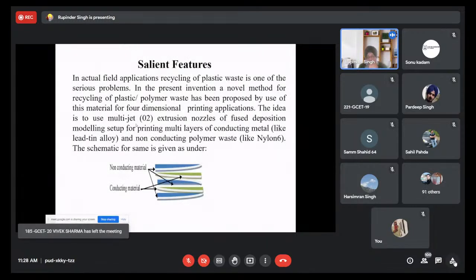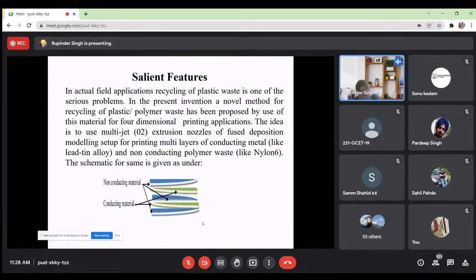Now the 4D part, this is derived from a very simple experiment of the first year in my BE program. Here what we did is we printed some layers like this. Here is a non-conducting layer, then the conducting layer, then the non-conducting, then the conducting, and then the non-conducting. Basically, the idea is to print a multi-material. So some non-conducting ABS or polyamide, whatever nylon you can use. Then for the conducting, this has been reinforced with graphene. Then the ABS or nylon, then with graphene. So I got a multi-material printed component.